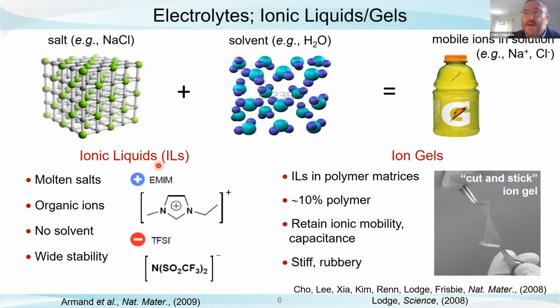There certainly are. There's an enormous class of compounds, it turns out. They're called ionic liquids. And what they are is essentially molten salts that are composed of large, mostly organic, bulky asymmetric ions. These ions are bulky and asymmetric to the point where they can't close pack. Because they can't close pack, they have low forces of interaction, which makes them molten already at room temperature. There's no solvent here. They're 100% concentrated. They're essentially liquid versions of sodium chloride at room temperature.